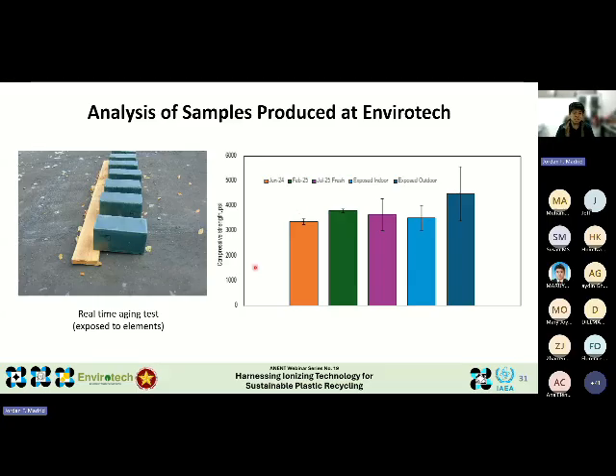The only noticeable change was in color, which we suspect is due to UV exposure. But aside from this surface effect, the strength of the samples remained relatively unchanged. This is a very encouraging result because it demonstrates that the materials not only perform well initially, but also retain their strength after real world weathering.